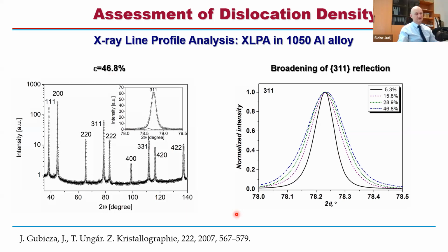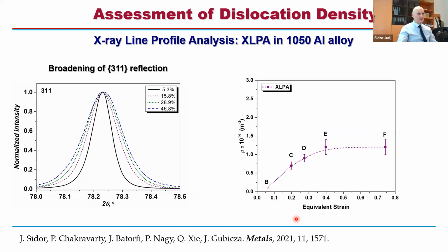And then the group of Thomas Ungar, basically, who started this assessment a long time ago, a group in Budapest, developed a method to estimate the evolution of dislocation density. So you do an X-ray measurement, and then you compare those lines with respect to the virgin one, and based on this you are able to predict the amount of dislocations which have evolved. Right, so what we see from the X-ray line profile analysis is that with increasing rolling reduction, the amount of dislocations tends to increase, to the power of 10 to 14. This is the range we typically expect in deformed materials subjected to 40, 50 or higher degrees of straining, right?